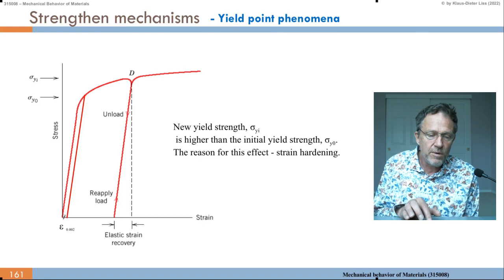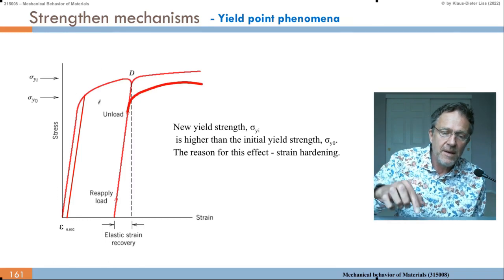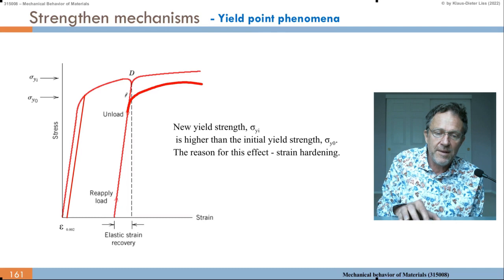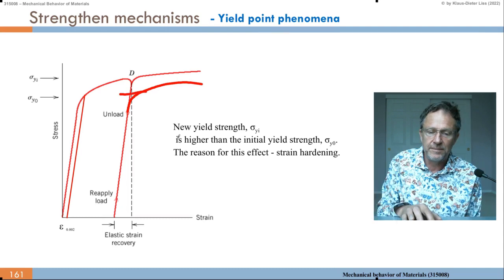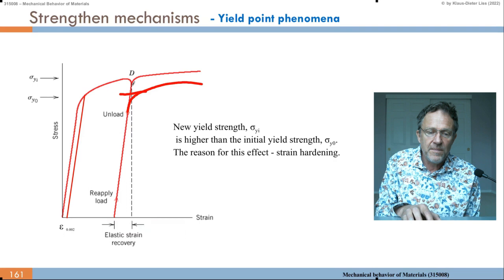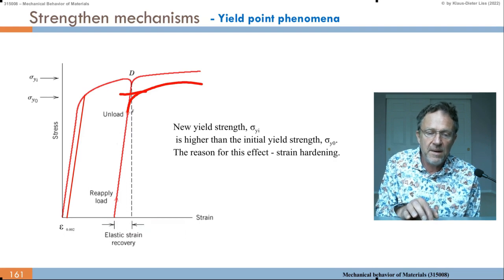Of course, now I can be smart, I can say I do this curve, I unload here, then I anneal at this point, then I would reproduce here the first curve again. So I would get sigma yield 0. But once we unload, the dislocations remain in the system. And then we load again, so these dislocations are already in the system, and therefore the material is harder. So sigma yield the second time is higher than the sigma yield at the first time.